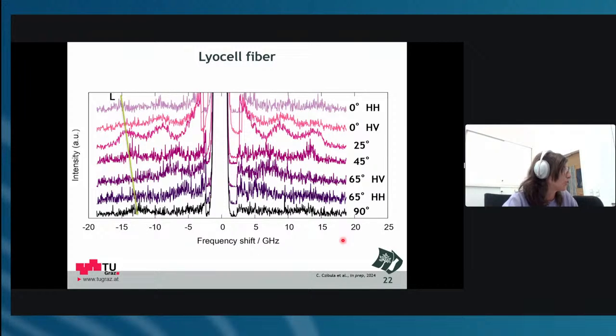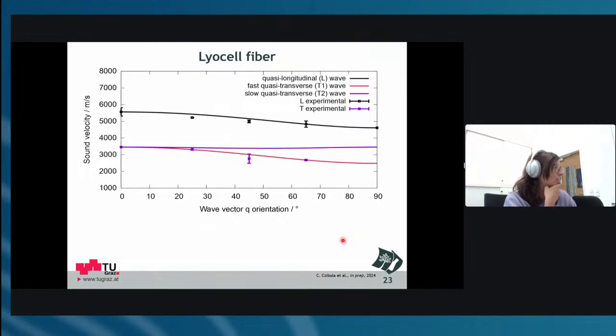We found here one longitudinal mode and again a transverse mode. When we tried to do the evaluation with the assumption that also here C44 is C66, it did not work out. So here we actually get that there should be a second phonon mode. And again, the longitudinal mode is really nicely fit, so the sound velocity is a good fit. I should also mention in these plots, which are very unfamiliar and hard to describe, that in these formulas, with this plus and minus, this difference, there is a certain relation. So you cannot just randomly fit in there.